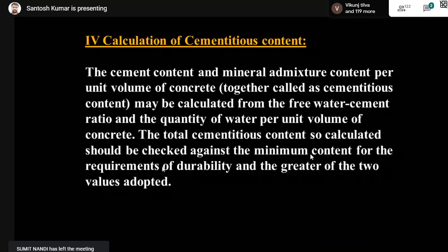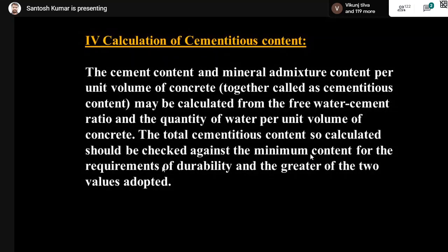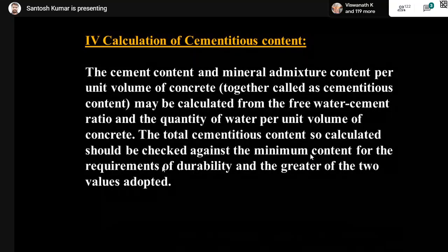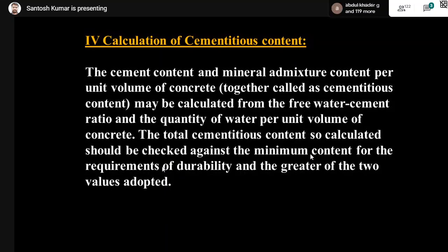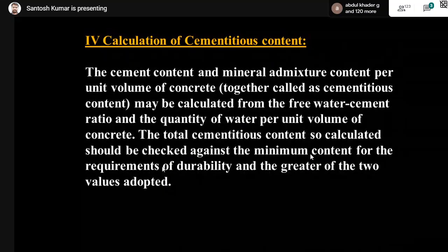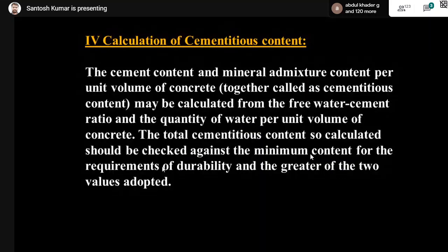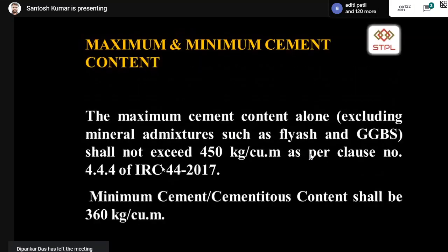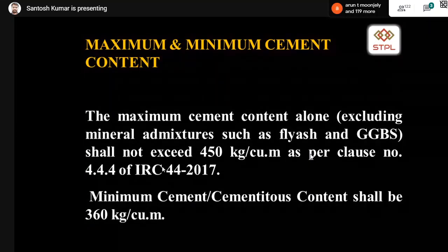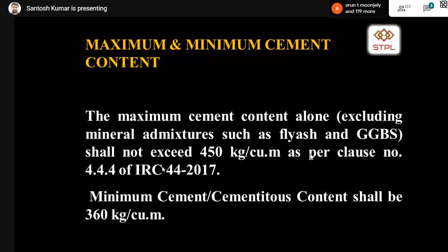So, calculation of cementitious content. The cement content and mineral admixture content per unit volume of concrete, together called the cementitious content, may be calculated from the free water cement ratio and the quantity of water per unit volume of concrete. The total cementitious content so calculated shall be checked against the minimum content for the requirements of durability, and the greater of the two values adopted. So we all know 450 kg is given in IS 456 and the same is implemented in IRC 44 also.